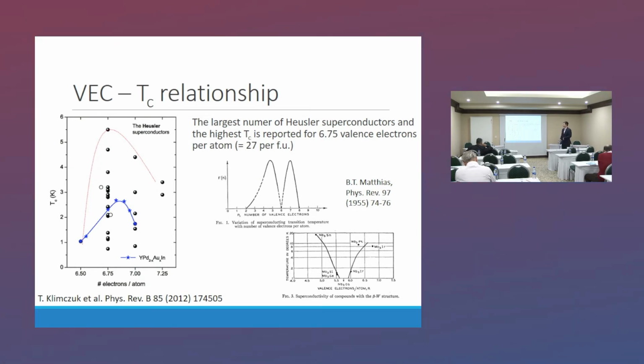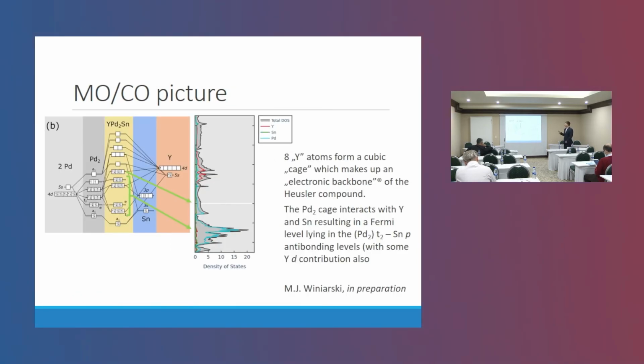several Heusler superconductors, palladium-based Heusler superconductors, and found that the largest number is found for 27 electrons per formula unit, and actually also having the same Tc, which is disturbingly similar to what was observed by Matthias for simple alloys. The molecular orbital picture for all those compounds is very similar.